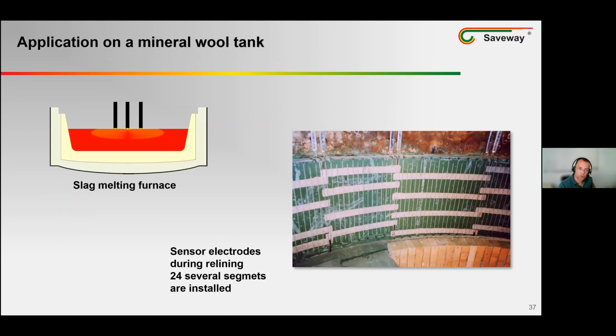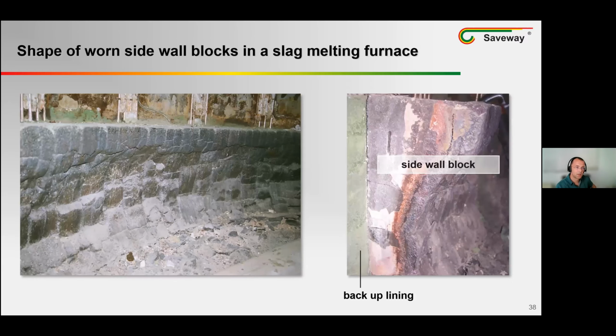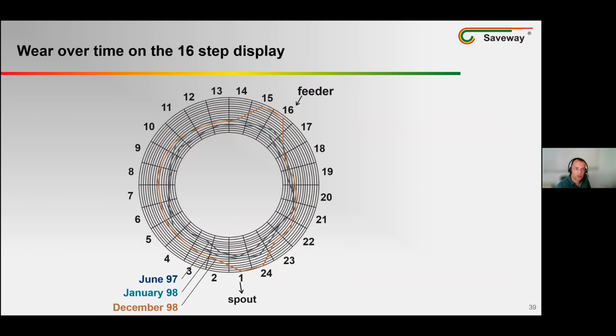The photo shows you sensor electrodes during relining. 24 segments are installed behind the side wall block. The sensor will be laid between the sidewall block and the backup lining. As we can see from the picture, the lifetime of the lining is about 1.5 years here. The wear of the furnace lining gradually expanded, and the wear of the spout and the feeder was the most serious.